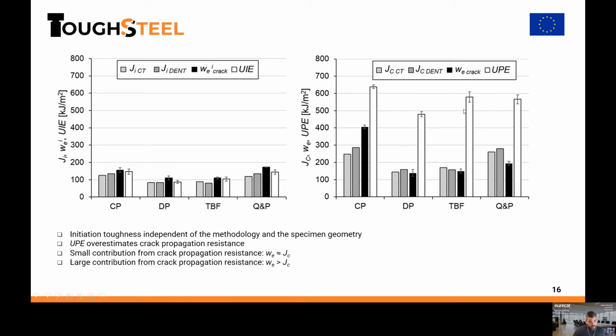But also, if we take a closer look at the material ranking that we can obtain using this kind of testing, we can see that we must be careful. For example, we're looking at this TBF steel, which is a third generation TRIP-assisted steel, which has an important contribution from the plastic work to the fracture energy. You can see that it has a really large unit propagation energy, almost comparable to the complex phase, and more or less equivalent also to the quenching and partitioning steel.